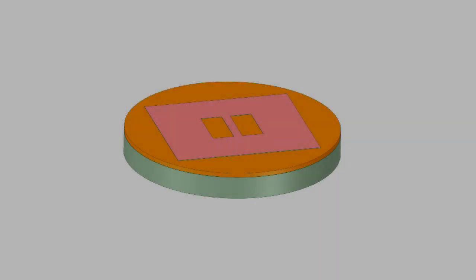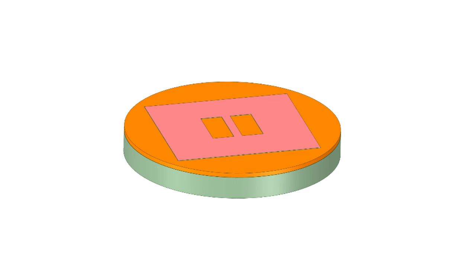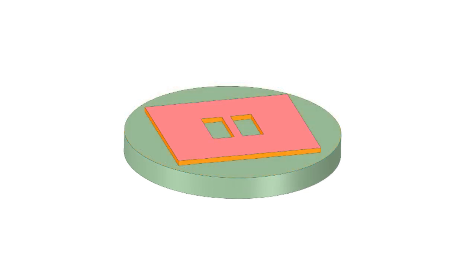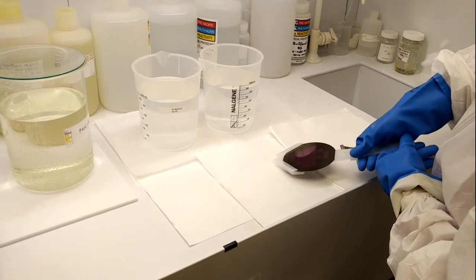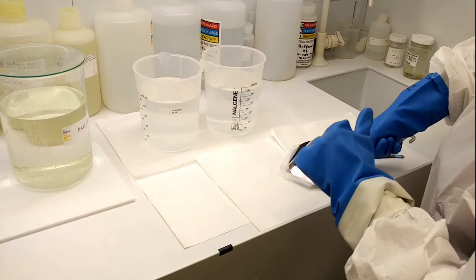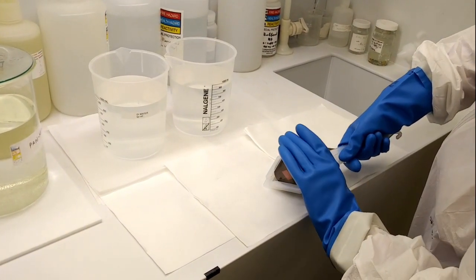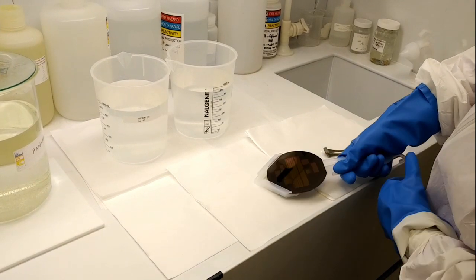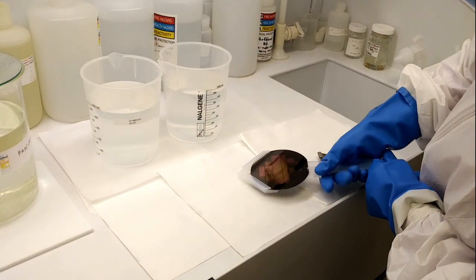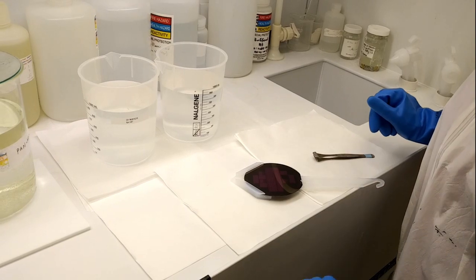The next step is to etch the silicon oxide layer using hydrofluoric acid. This will remove all the silicon oxide that is not covered by the photoresist pattern. Hydrofluoric acid poses a health hazard to those working with it. In the case of accidental splashes, proper personal protective equipment must be worn, such as heavy gloves and a face shield, to ensure no contact with eyes, face, or skin is possible.